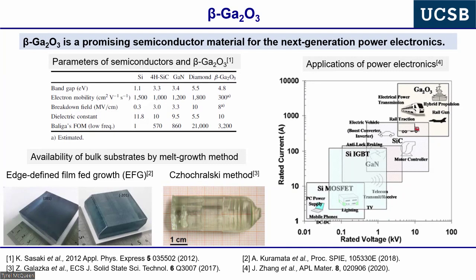So beta gallium oxide can be grown by the Czochralski method, but the preferred method right now, which produces the substrates that are used for almost all the device research, is the edge-defined film-fed growth method, the EFG method. This is also used by some companies to grow sapphire, okay? And this produces slabs that are on the order of half a centimeter to a centimeter to a few centimeters thick, but in the long direction, the slabs can essentially have any dimension. So this has already been commercially available at 4-inch, demonstrated at 6-inch and 8-inch. This lateral dimension can keep scaling with the EFG method.